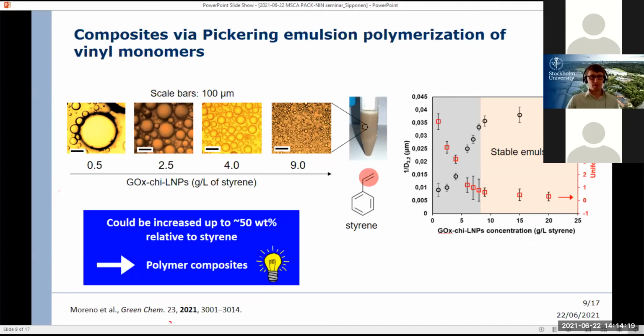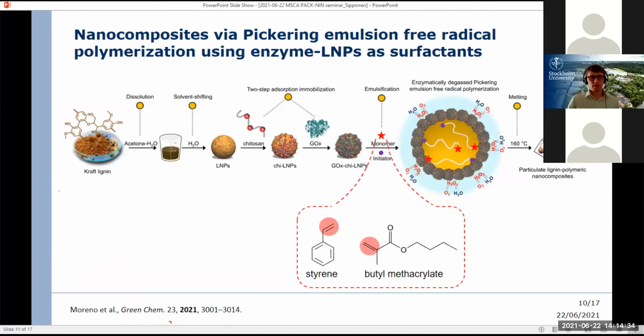with good properties. And basically it was a kind of side invention here that we found that we can actually increase the lignin particle concentration quite significantly to make these composite materials. So we focused on this in a follow-up paper that was recently published, and we took polystyrene and PBMA as the focused polymeric systems that were in this case produced by free radical polymerization.